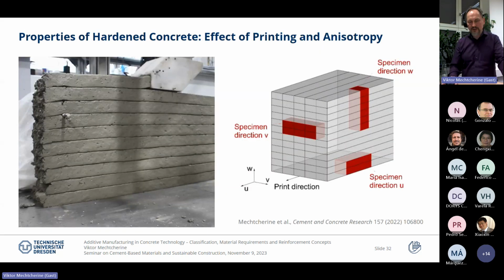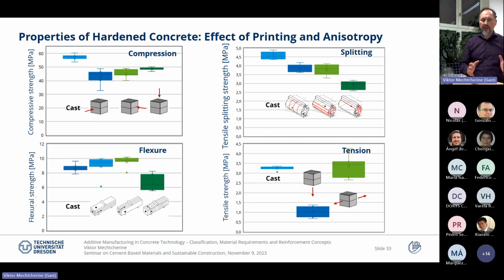After producing some walls, we also, of course, want to test the properties. And here I want to emphasize that, of course, due to this layered structure, the properties will not be the same in all directions. And this is why we need also to actually take specimen in different directions, also test them in different directions. And we see here some effect of this direction. We have here so the cast specimen on the left as a reference, and you see that specifically if you test flexural strength or tension, you will see that applying the force perpendicular to the joints will of course result in slightly or sometimes considerably lower values of the strength in comparison to the direction of loading parallel to these layers.